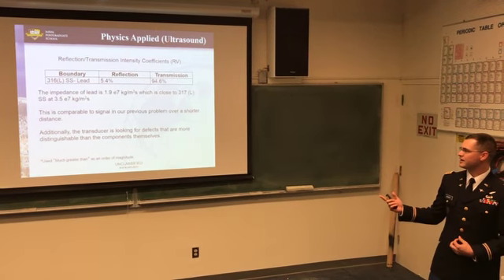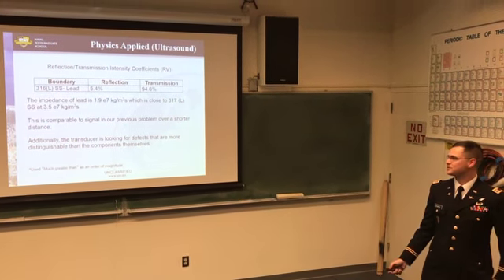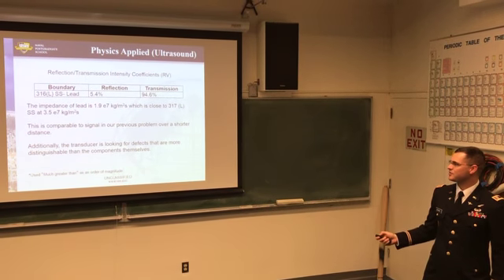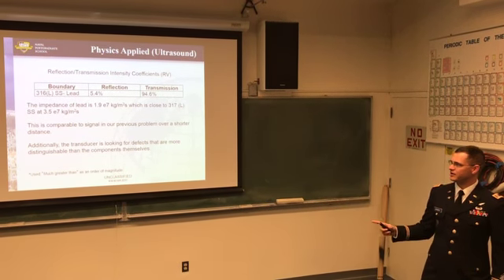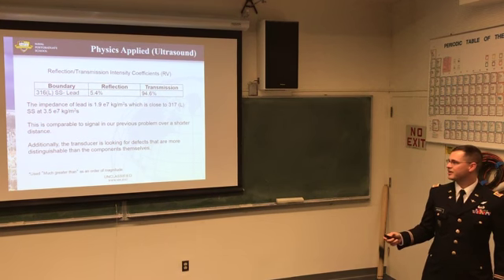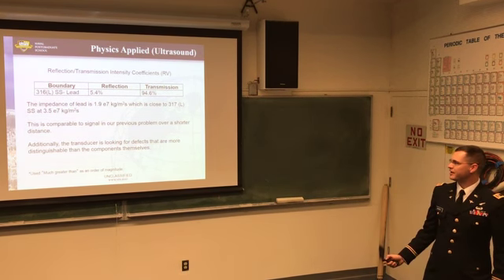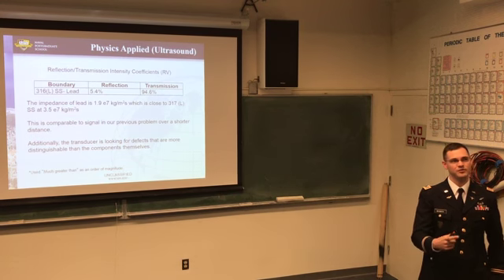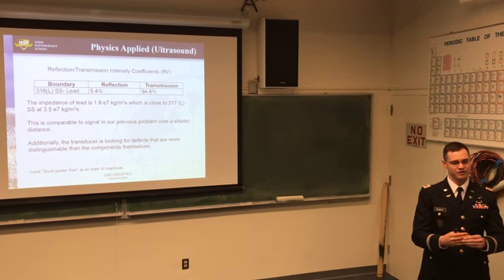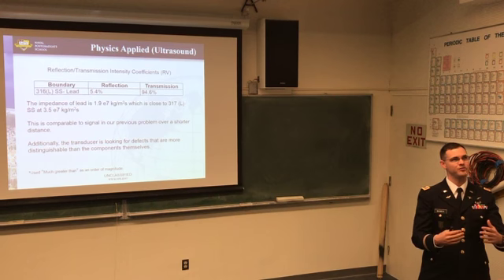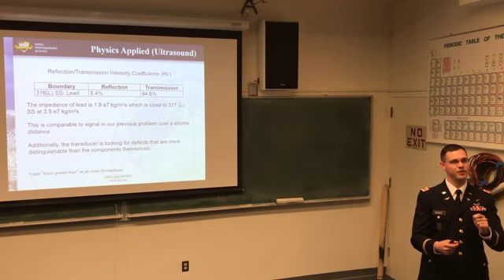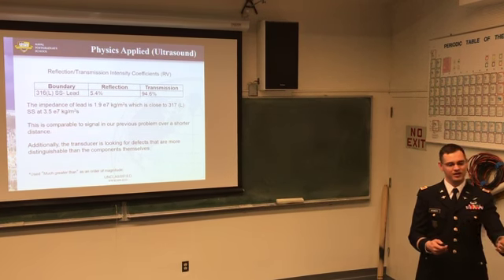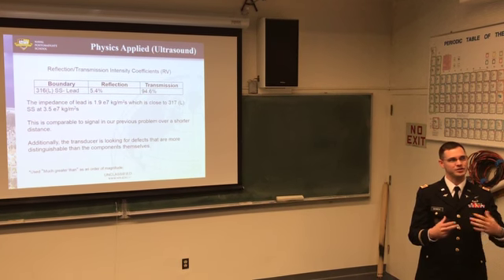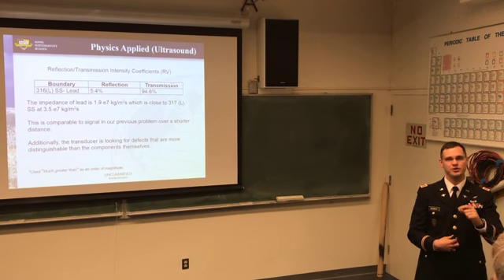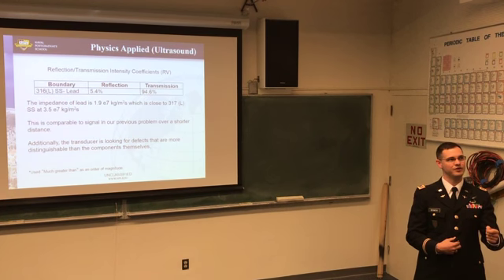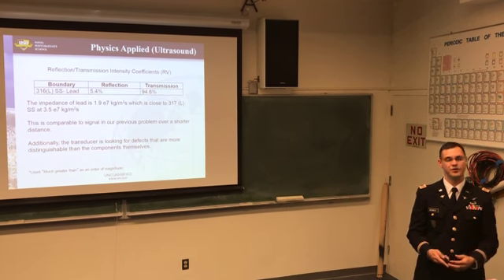And then looking at the reactor vessel boundary for your reflection transmission, you get about the same 5.4%, but it's a very short travel distance, so you get almost no attenuation. And when you're looking at the reactor vessel, you're looking less for what the picture is, and you're looking more for defects. So if you have a defect, it's going to greatly increase the acoustic impedance at that point, and you'll get a very clean signal back. So it's actually good that we don't get a lot of reflection at the boundary, because you're looking for things that are wrong on the reactor vessel, not a clean signal going through.